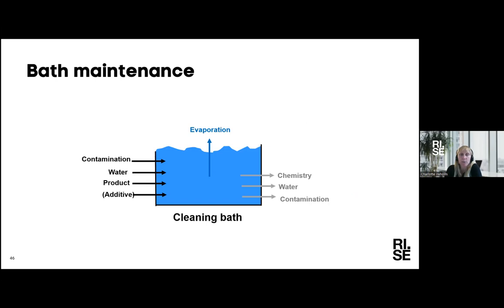So we've been talking about washing liquids, and then often you have a bath. If you have an open bath, then of course some of the water evaporates, so you have to adjust and add some water, and also some of the additives and the chemistry in the bath is used during the cleaning, and you have to add that. If you have a continuous production, for example, make sure that the cleaning bath is in balance and fresh enough to take care of the contaminations that we want to clean away. I don't think I mentioned so much more about that.